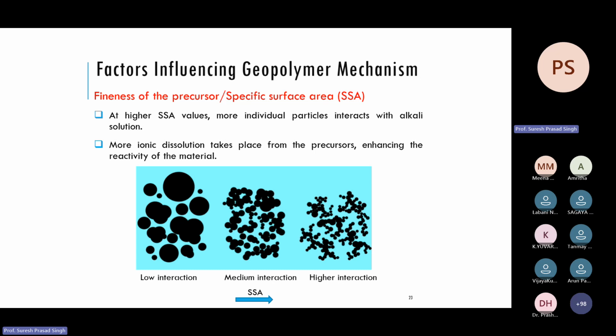And if you grind the material, you have seen these fly ash particles, schematically, which are spherical particles. Suppose you grind it, it becomes smaller particles and its specific surface area increases. Again, if you grind or pulverize this, it will have a very high surface area. Because the release of silica and alumina occurs from the surface only, if the surface area increases, the release of silicon and alumina ions will also be very fast, the geopolymer product will be very strong, and a large amount of it will be produced. So more ionic dissolution takes place from the precursor, enhancing the reactivity of the material. So this is about the fineness.